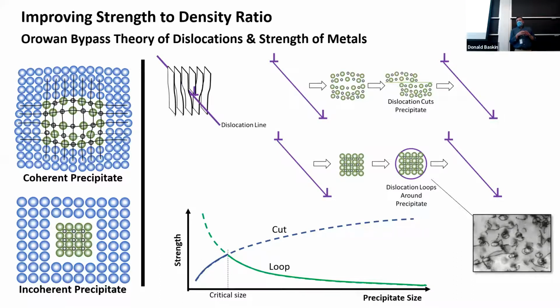They were heating this thing, and I think it was some 300 or 400 degrees Celsius in a furnace. If they had just left it there for a couple of minutes, it probably would have been fine. But the problem is in the actual factory environment, they were leaving this aluminum housing in a furnace for like 6 hours. So they would get the motor installed in the aluminum housing, we would get the part back at the company I was working at, we would test them and they would fail. The aluminum would burst into a zillion little pieces. And the reason for that was that they had overaged. They had coarsened the precipitates to the point where they weren't strengthening effectively.